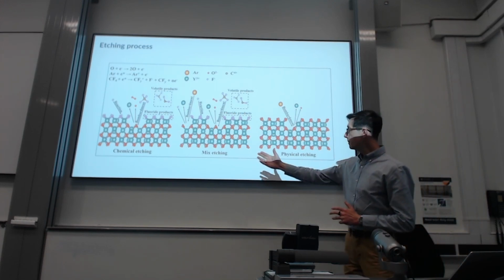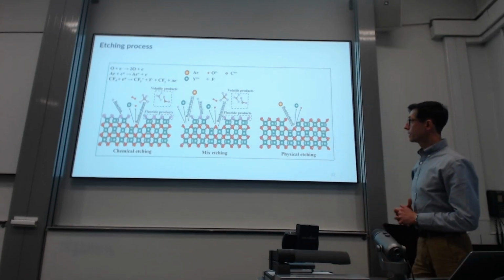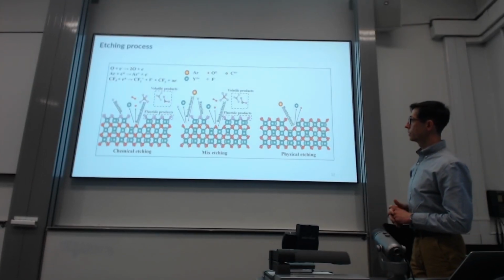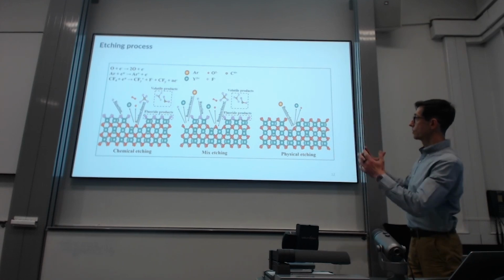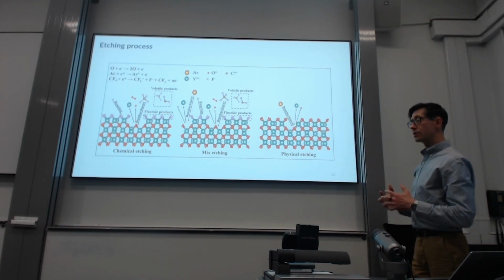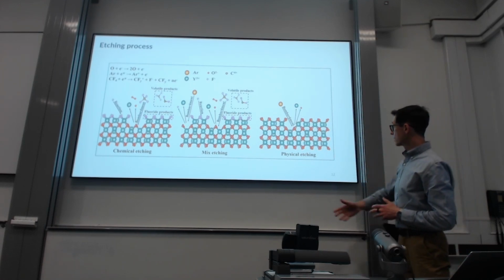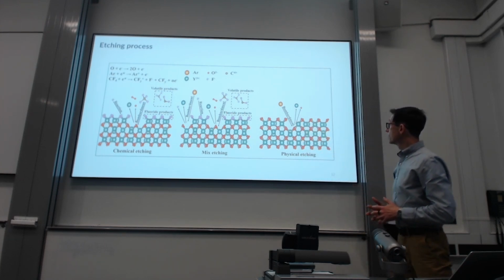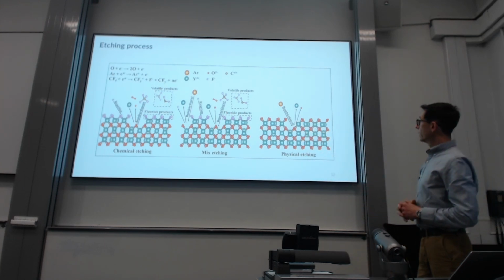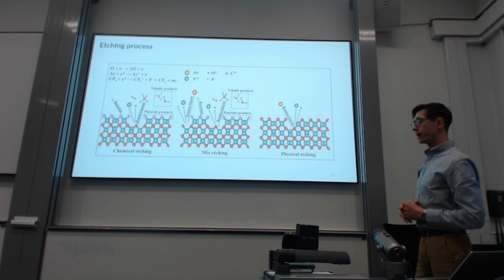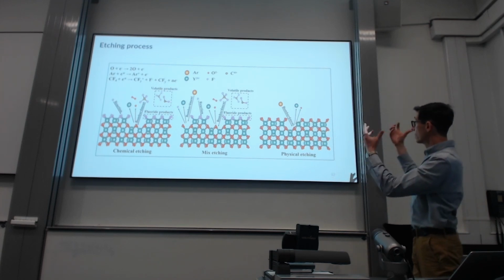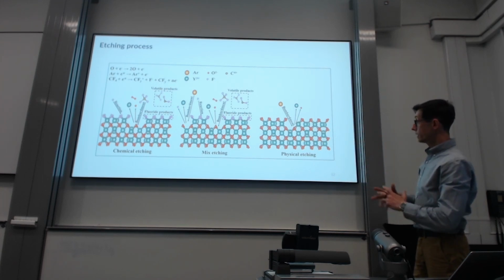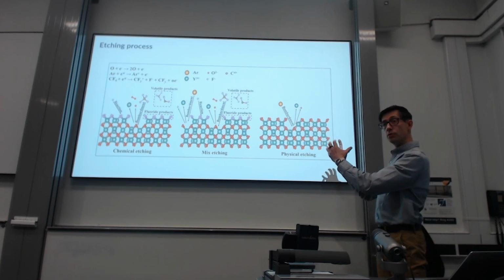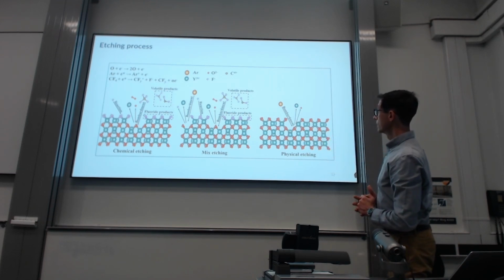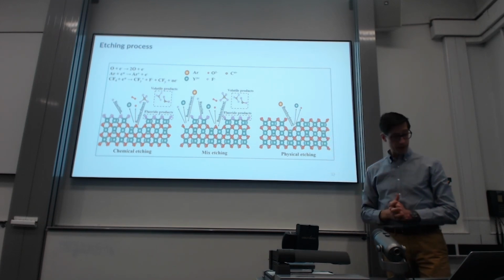So in terms of chemical etching, you have chemical interactions happening on the surface. You have your fluorine products. You produce your volatile products. You have reactions going on the surface. In terms of physical etching, it's a very simple bombardment mechanism of the argon atoms and removal of the particles. And in the mixed case, of course, you have those two processes taking place at the same time.